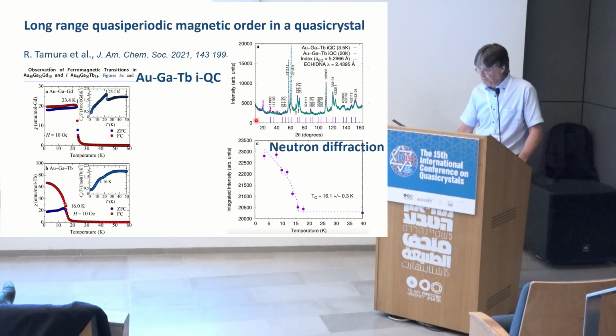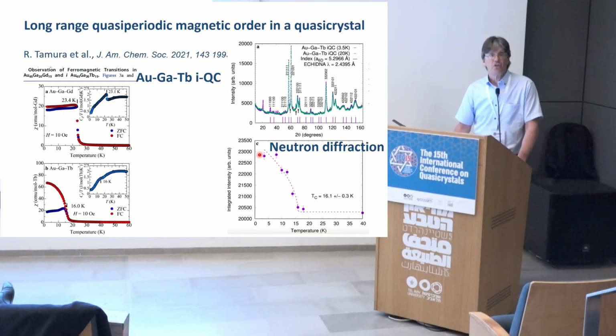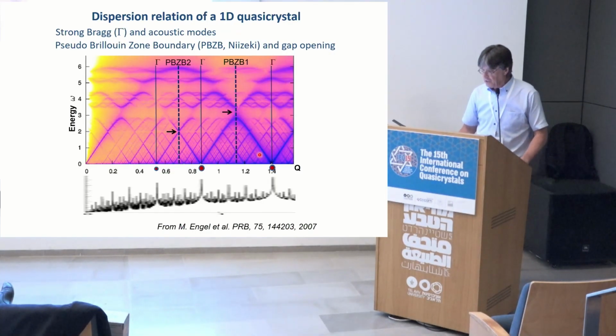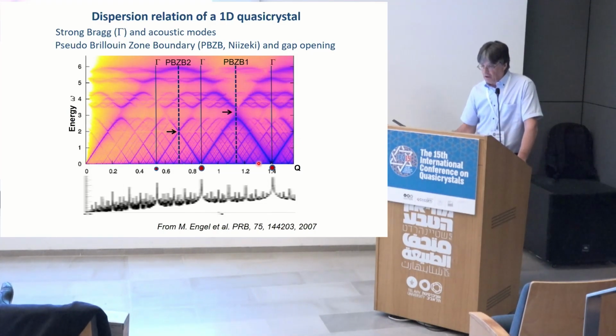But it's also shown by this nice neutron experiment, where you go below the magnetic phase transition and you see that some bright peaks are showing up, and these are magnetic Bragg peaks, which is a clear cut sign of the magnetic long-range order. A few words on phonons and phasons, and then I will come to the conclusion. So phonons,